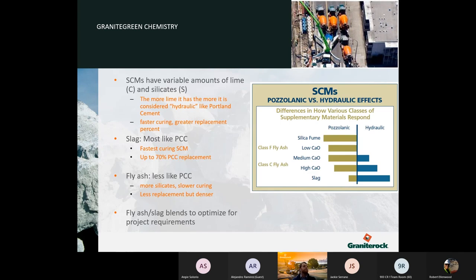A bit more on the chemistry. They have varying amounts of lime. The more lime that it has, the more hydraulic it is considered, like Portland cement. So those are faster curing and can replace cement at greater percentages. Slag has more lime, so it's more hydraulic. It's the fastest curing SCM and can replace as much as 70% of Portland cement.